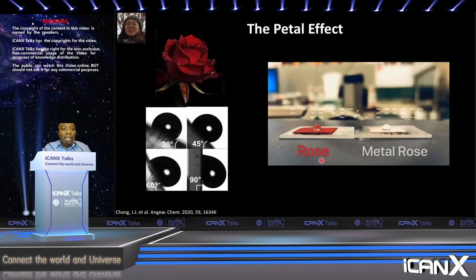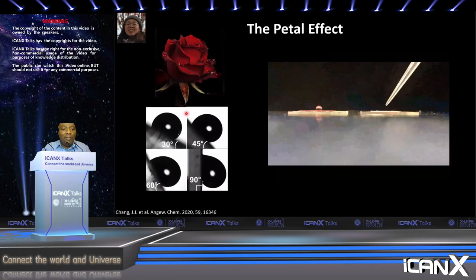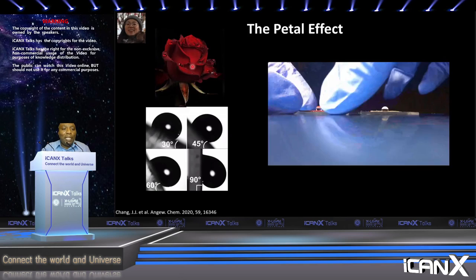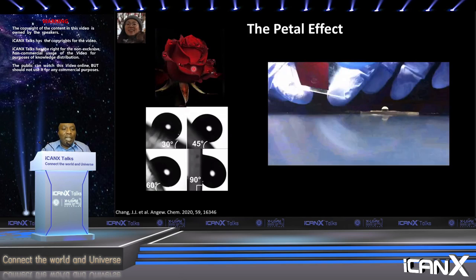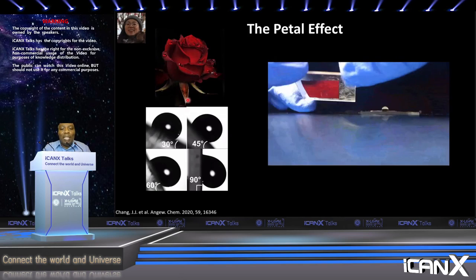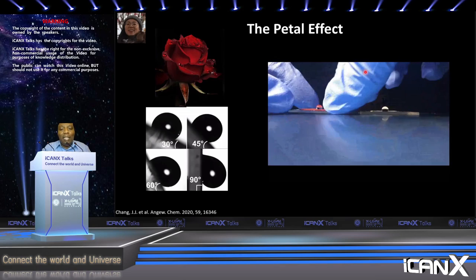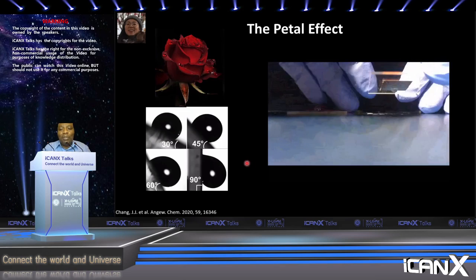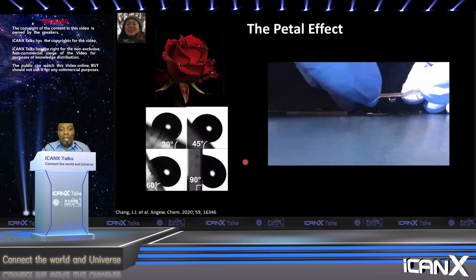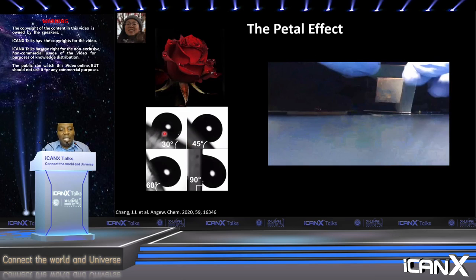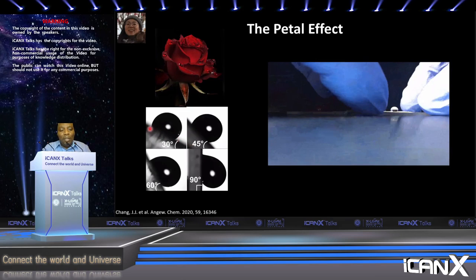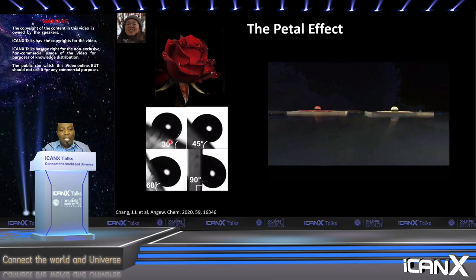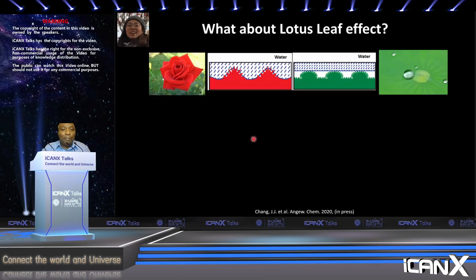Then, if we're making a rose flower, of course, we have to look for hydrophobicity, because these structures are known to be self-cleaning, but they self-clean in a way that the droplet actually adheres to the surface of the rose. And when we tilted a droplet of water on our surfaces, we see that it doesn't go off. And as is shown in this video here, actually you can flip them upside down and it doesn't fall off, just like in the rose petal.